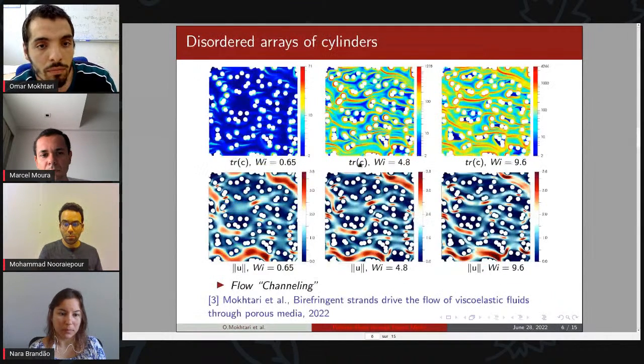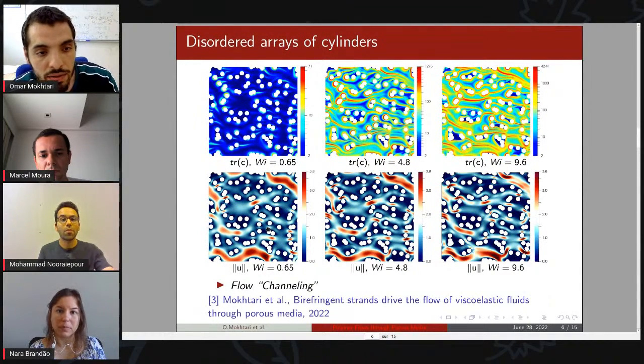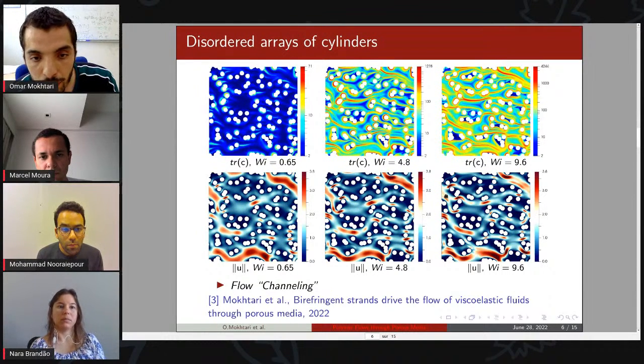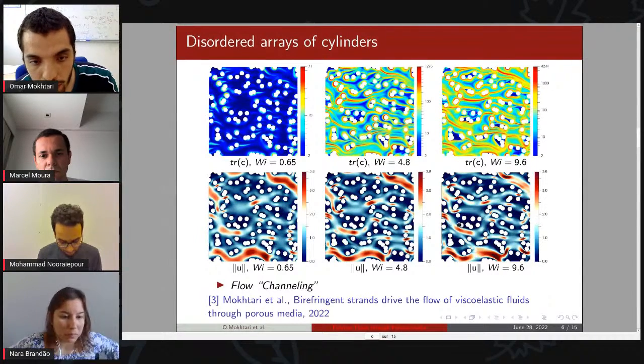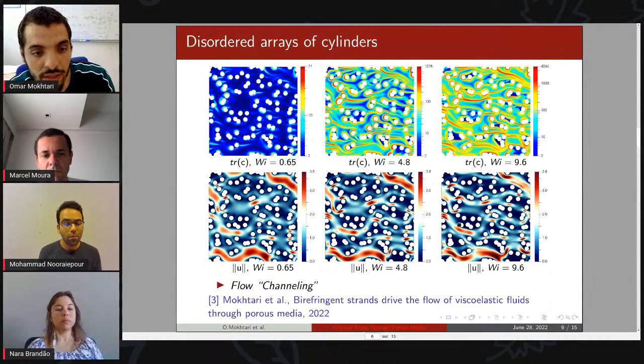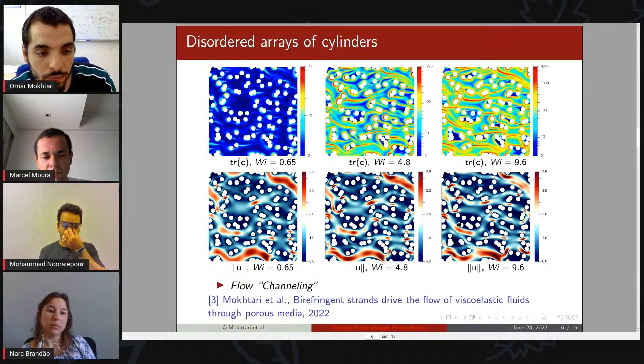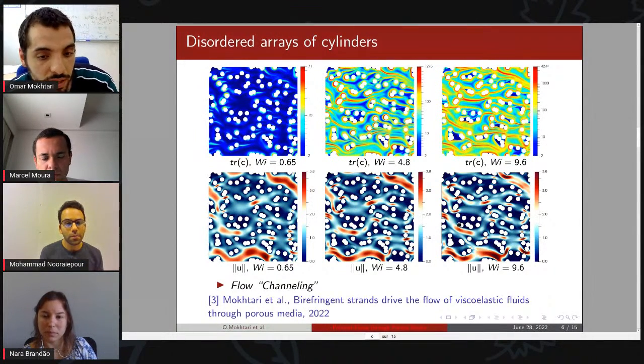And in more complex structures, such as disordered arrays of cylinders, this mechanism can explain the channeling of the flow, with the same effect of amplification of preferential flows and more stagnation zones here. The question that arises is what happens in ordered arrays of cylinders, where by definition there is no pre-existing preferential flow.